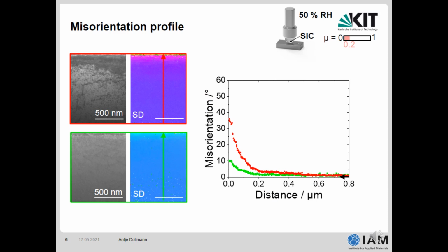I have used the TKD measurement also to investigate the misorientations. So here I have analyzed the misorientation profiles along the arrows in the TKD measurement. The distance of 0 microns means that there is the surface, and 0.8 is in the bulk. And so we see that the misorientation has in both grains a strong increase starting at around 0.2 microns. And in the red profile, there's also a discontinuity, and this matches with the dislocation trace line. Furthermore, we have also a difference of around 25 degrees in the maximum misorientation of the two grains. And I think that this comes from the different initial grain orientations.